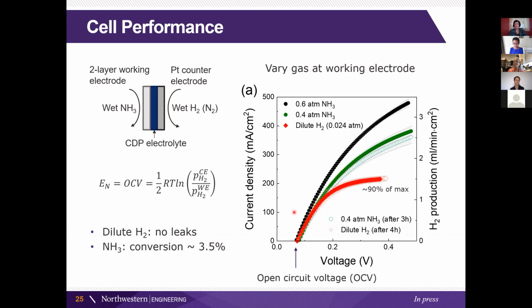And what we can see is that if we deliver ammonia to our cell, we get current density out of it. And we want to show you that that's exactly equivalent to the hydrogen that's being produced. So if we have 100% Faradaic efficiency, that means that every single electron that goes across through our exterior circuit is balanced by a proton that's going through our electrolyte. And so we can compute then the hydrogen production.